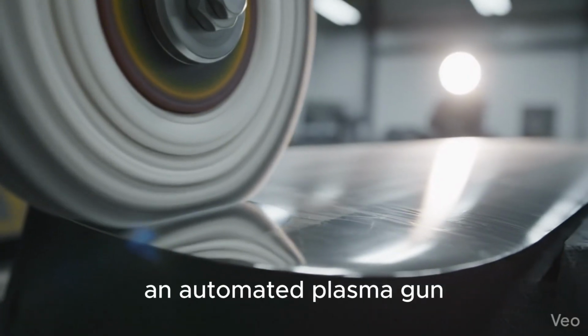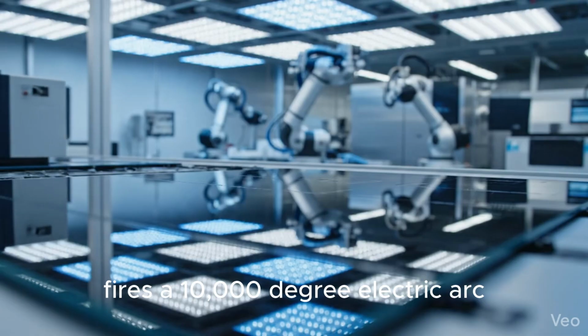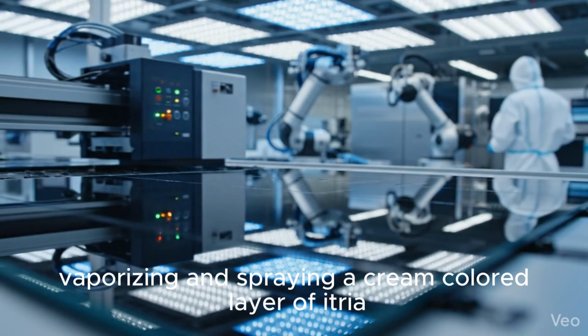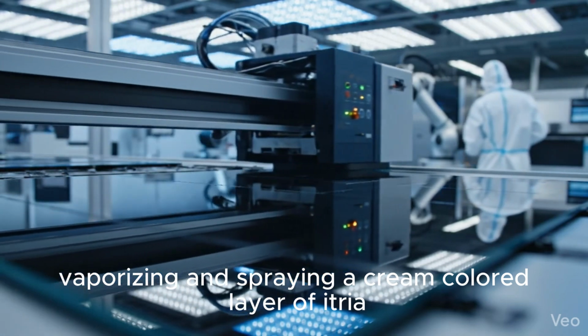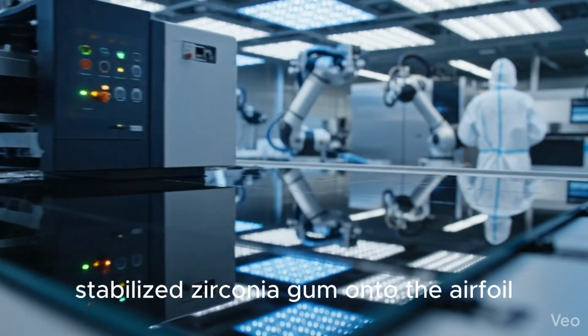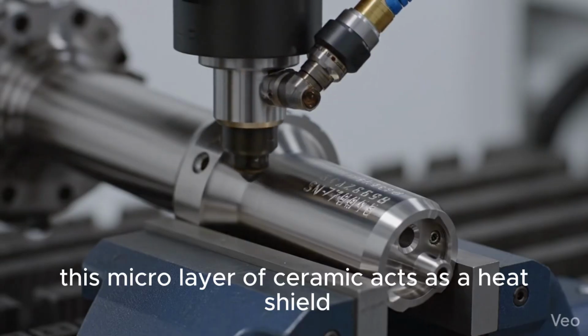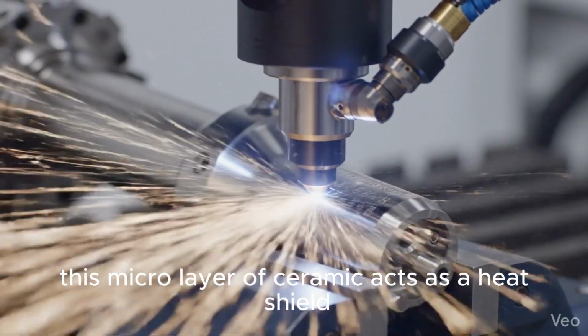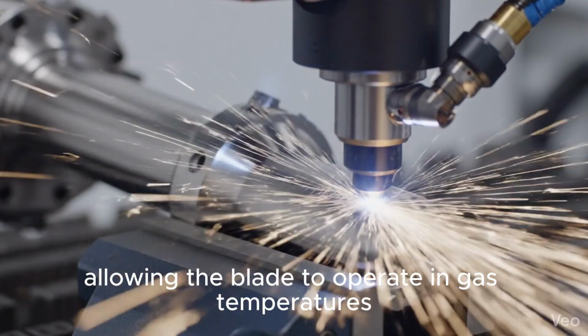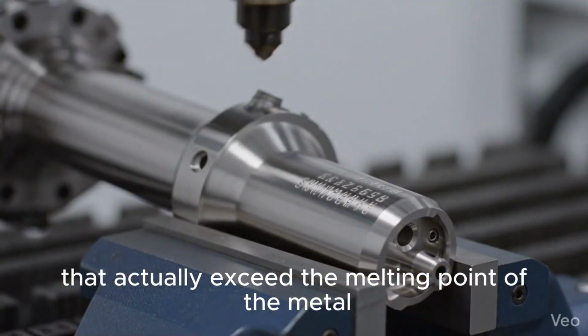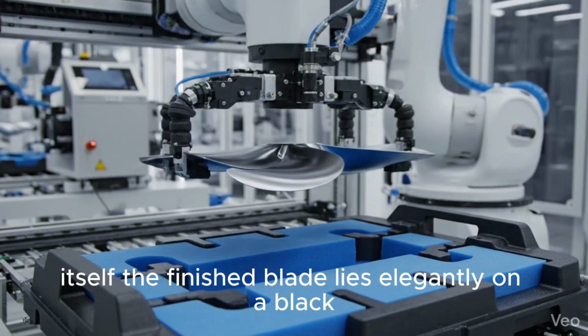Here, an automated plasma gun fires a 10,000-degree electric arc, vaporizing and spraying a cream-colored layer of yttria-stabilized zirconia onto the airfoil. This micro-layer of ceramic acts as a heat shield, allowing the blade to operate in gas temperatures that actually exceed the melting point of the metal itself.